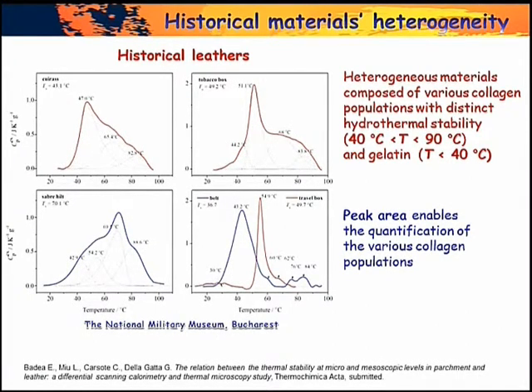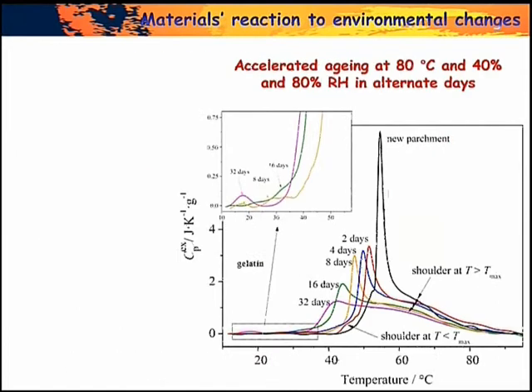Also historical leathers present a very high level of heterogeneity. So, the problem is that being so heterogeneous, all these components of collagen and parchment will react differently to various temperature and relative humidity conditions. So, in order to evaluate the response of this collagen population to temperature and relative humidity, we perform many accelerated aging treatments.